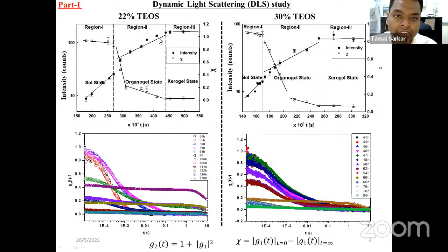And by the time the gel reaches here, most of the solvent of the gel gets released, and there is no more change of intensity with time. That means the gel has completely become a xerogel. Now a similar intensity profile pattern was also observed for the 30% TEOS case, where the gelation and the xerogelation happened quite earlier than for 22% TEOS. So the point of taking two different concentrations was to see whether there is any effect of TEOS concentration on the gelation or xerogelation time.